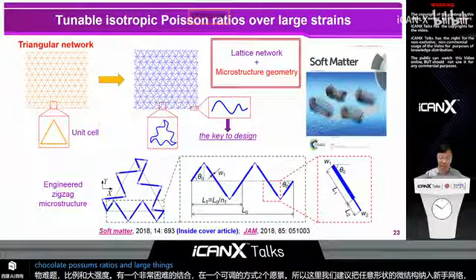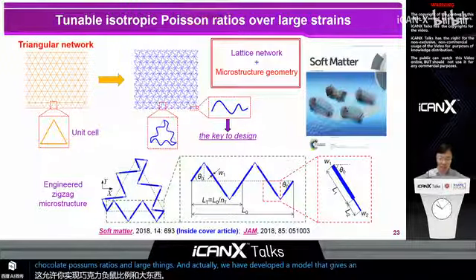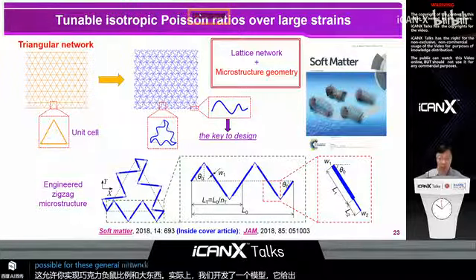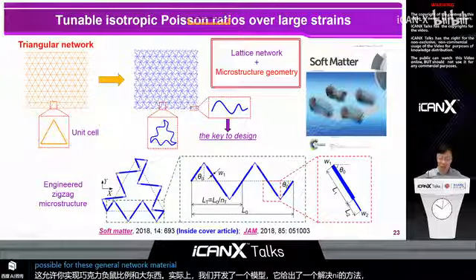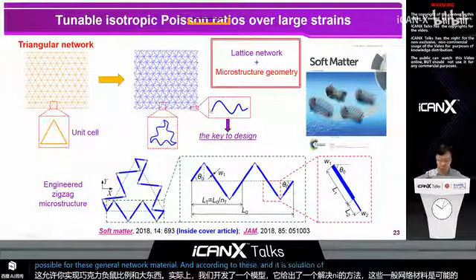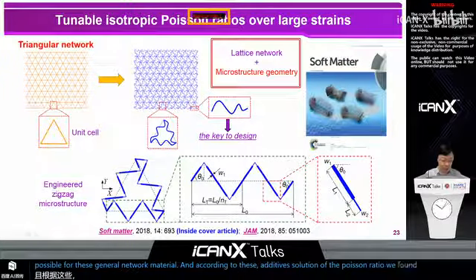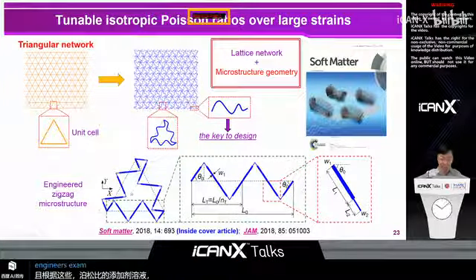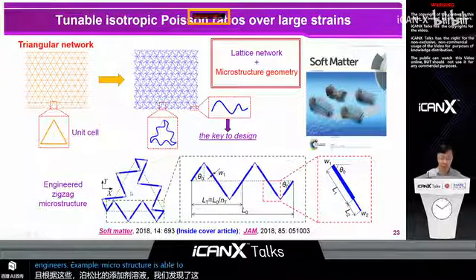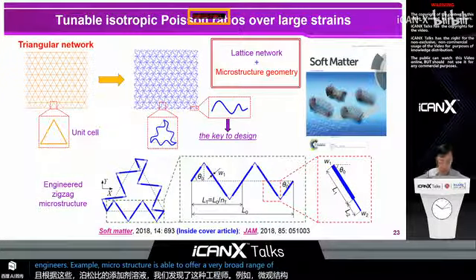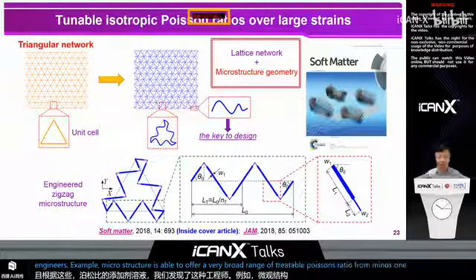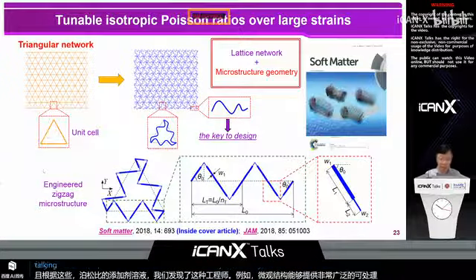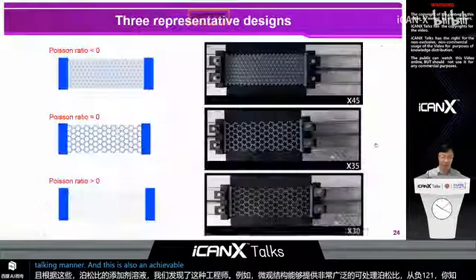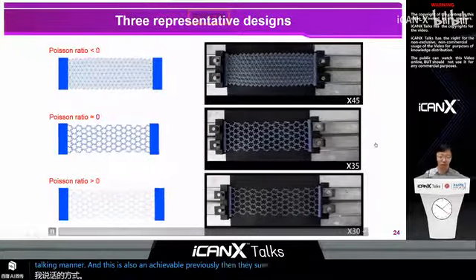And actually, we have developed a mechanics model that gives an analytical solution to the linear Poisson's ratio for this general network material. And according to this analytical solution of the Poisson's ratio, we found that this kind of engineered zigzag microstructure is able to offer a very broad range of tunable Poisson's ratio from -1 to 1 in an isotropic manner. And this is also unachievable previously. Let me show you a video about what we can achieve.